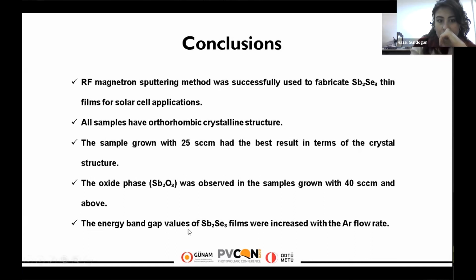The energy band gap values of antimony selenide films were increased with the argon flow rate. So with this study, we show that argon gas flow rate can be a parameter to obtain good quality antimony selenide films as an absorber layer.